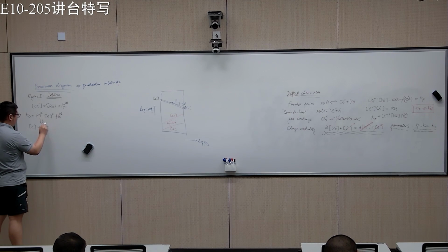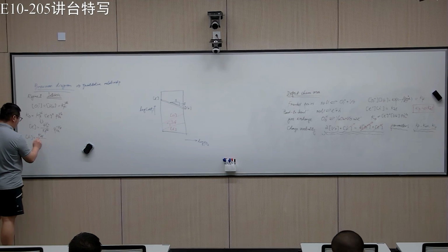Then what you get is electron equals square root of KO over Kf, then move the PO2 here, to the power of -1/4. Then holes is basically KEL over electrons. Then you just do the calculation.